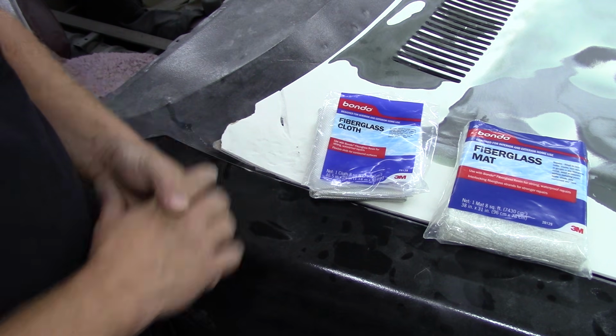So thanks for tuning in to Heavy Pedal Garage. I hope this helps you understand what I've learned in the last 2 weeks, which is the difference between SMC fiberglass and traditional fiberglass, the materials that you need to use to make that repair. And also understanding the difference between cloth and mat, and when you would use cloth for structure and support and strength, and matting for building a surface. And lastly, that matting will not melt into your repair if you use true epoxy resin because of the styrene in that matting.